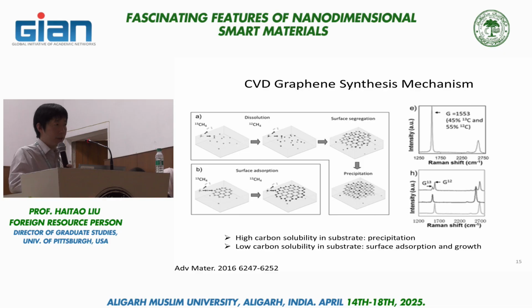So this is pretty much what people have been doing with graphene. Now I have to mention, people have figured out all kinds of ways of doing CVD synthesis using every imaginable precursor combination you can think of. Polymer, gas phase, even bird droppings can produce graphene. Pretty much any organic species can be used as a precursor. All you need is some kind of carbon radical, essentially, to be captured by the metal substrate, and then nucleate and grow a carbon sheet.